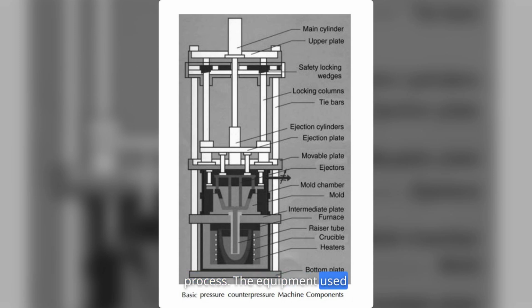The equipment used is similar to a low-pressure die casting machine. It is essentially a vertical press with a crucible furnace mounted under the press. The basic pressure counterpressure casting (PCPC) machine is shown in this figure. A unique feature of the PCPC process is that the horizontally parted die is surrounded by an airtight mold chamber.